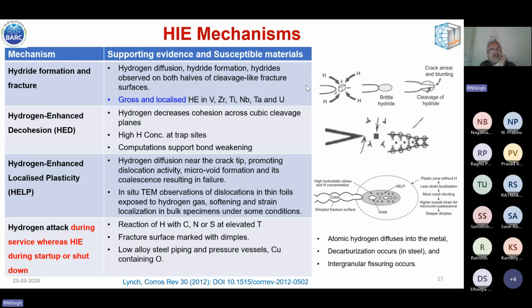Only in the case of hydrogen attack, which occurs at 550, 600 degrees Celsius for materials used in the process and power industry, this kind of embrittlement is observed. And there it is not because of hydrogen alone, it's because of a combination of hydrogen and some other interstitials like carbon, nitrogen, sulfur and all. If you see the earliest mechanism proposed for hydrogen embrittlement, it was that once hydrogen solubility is exceeded, hydrogen comes out and gets accumulated in the voids, and the pressure will be very large, and that will rupture almost any material. The pressure inside those voids would be of the order of several lakhs of atmospheres.